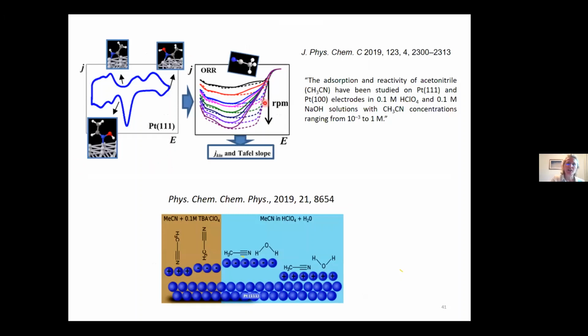This is a study by Herrero, Juan Feliu and Copa, where they were actually showing that if you look at this reaction and you start to put acetonitrile in, the adsorption of the acetonitrile on the surface is starting to play a role in changing the catalysis kinetics. So they were commenting at this point that acetonitrile is adsorbing. This paper here as well is also talking about how adsorption of acetonitrile can impact on processes.